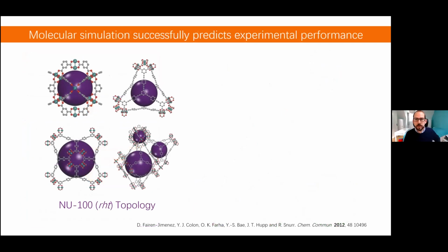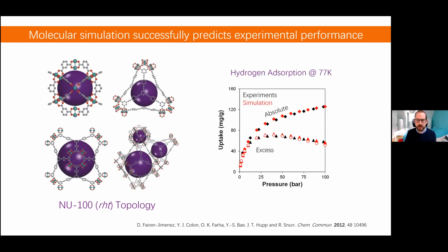Okay, so an example of these molecular simulations. Well, this is a paper that we published many years ago, 9 years ago, when I was working at Northwestern University with Professor Snurr. Basically we took a family of materials, not only this NU-100, but a family of materials, and we were interested in hydrogen adsorption. So we take the structure of the material, and then we start running molecular simulations, and we try to see if we can really predict the adsorption performance.